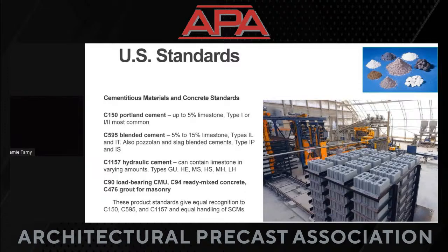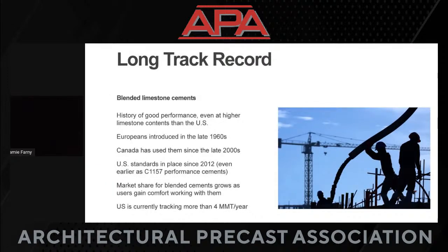They have other designations. So if you see a type GU, a general use cement designation, or an HE, high early, or an MS or HS, a moderate or high sulfate resistant material, then you'll understand it's just another way to specify a cement, and it actually has requirements for performance it has to meet, but it'll also behave like a Portland cement or like a PLC. Those are the cement standards that are then recognized by the concrete material standards, like C90 for load-bearing concrete masonry units, or C94 for ready-mix concrete, or C476 for grout for masonry. All of those standards recognize any of those 3 cement standards, and they say, hey, we can use all of these materials more or less equally, and we can still use our supplementary cementing materials, or SCMs, along with them.